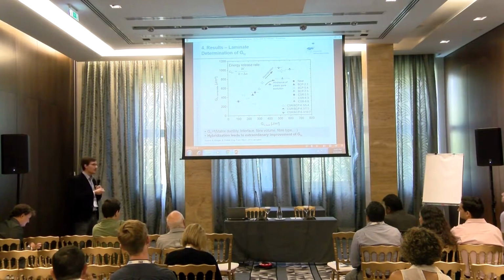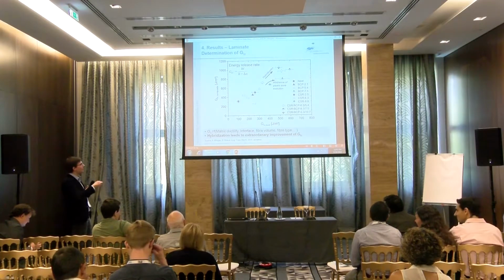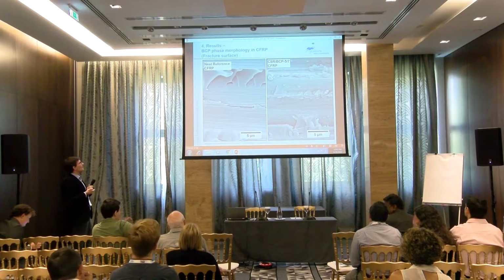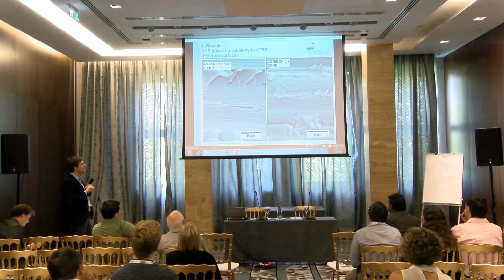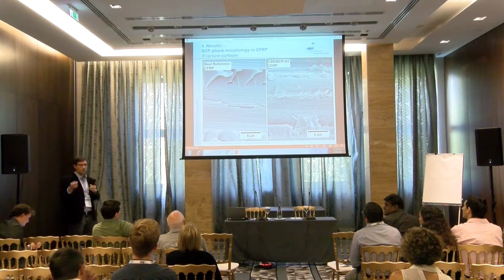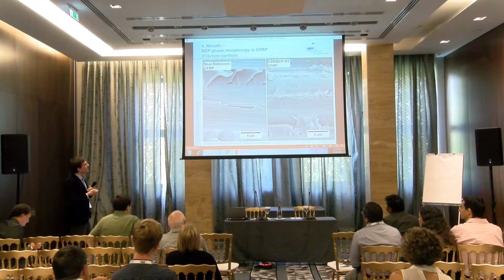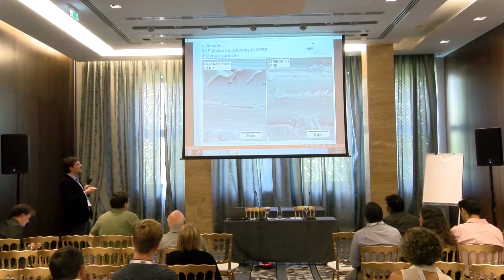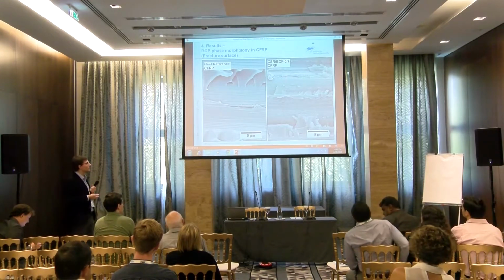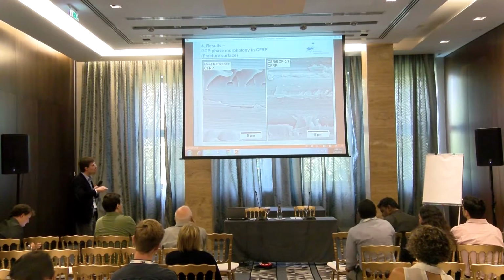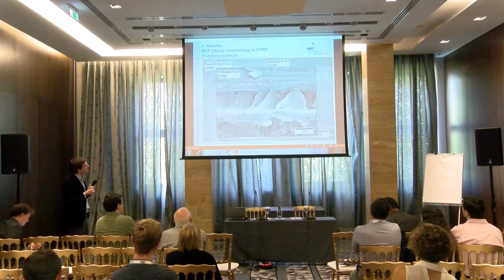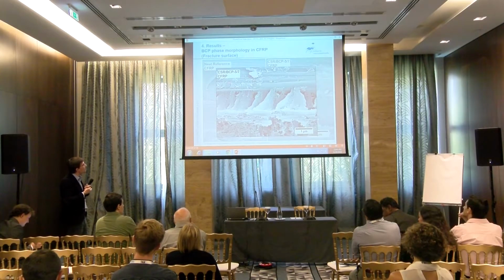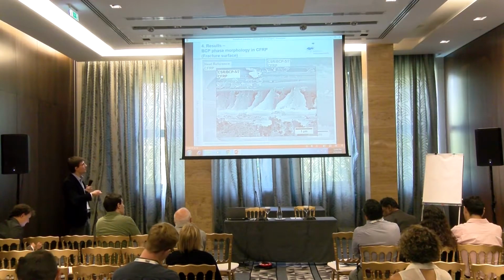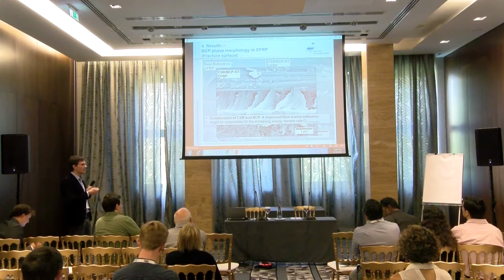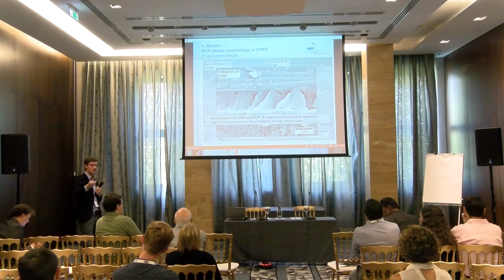We took a look at the interface, because that's one of the other factors which can influence this kind of trend. As you can see on the left side, we have a neat reference CFRP sample. We have some kind of bonding of the matrix, which is for sure required and expected, because it's a fiber with an epoxy sizing. On the other hand, same magnification, you see that we have a much more severe or stronger matrix adhesion to your fiber, besides the different look of your matrix. As you can see, we have a lot of matrix adhesion to the fiber in this higher magnified image. And that might be responsible for this increase in fracture toughness.